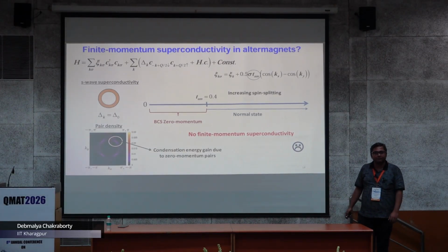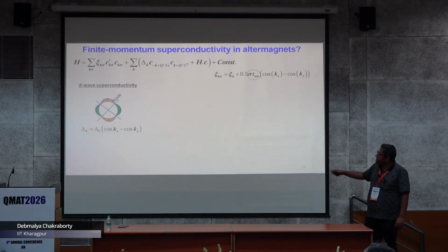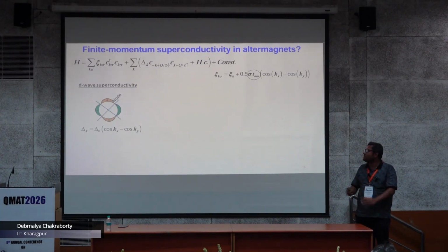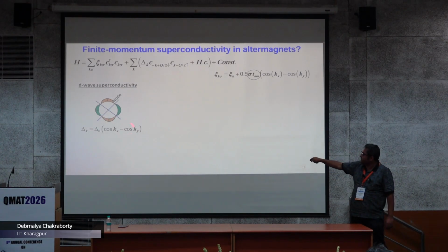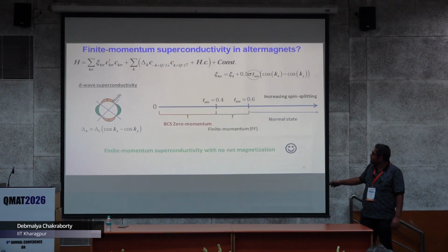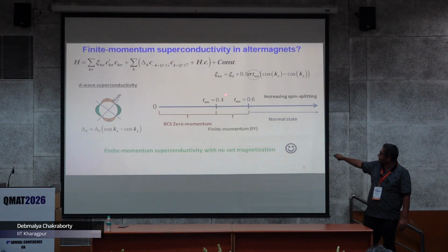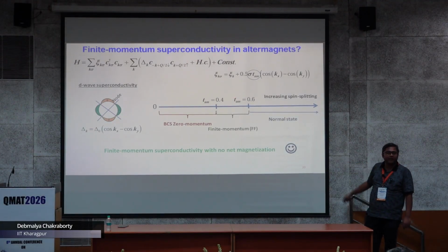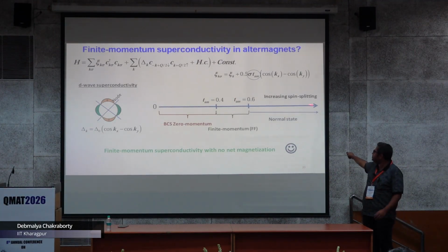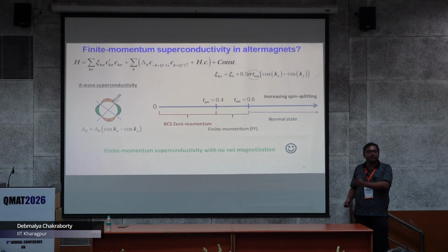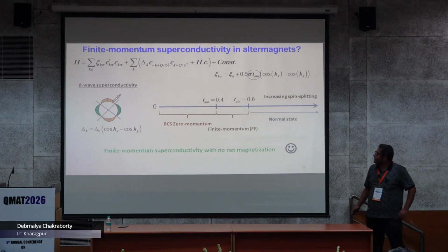Now if we consider a D wave with the same symmetry as the altermagnetism, that is dx square minus y square, then what we see is that we can actually get a finite momentum superconductivity without any magnetic field, with no magnetization. So we get a region of TAM where we get a finite momentum superconductivity, and then eventually if you increase TAM, it will go to normal state.